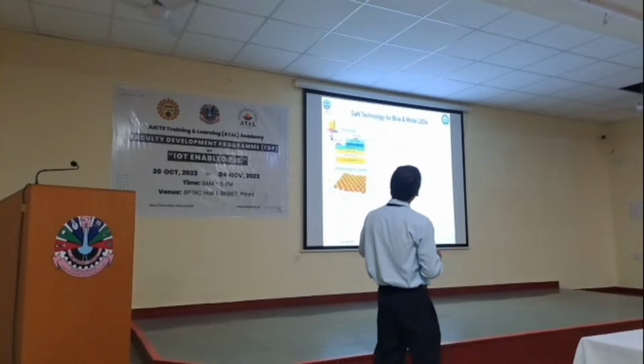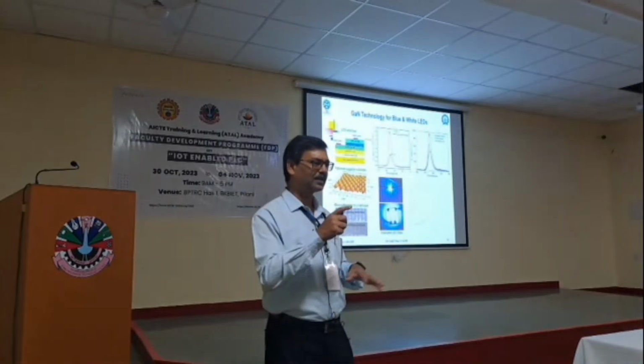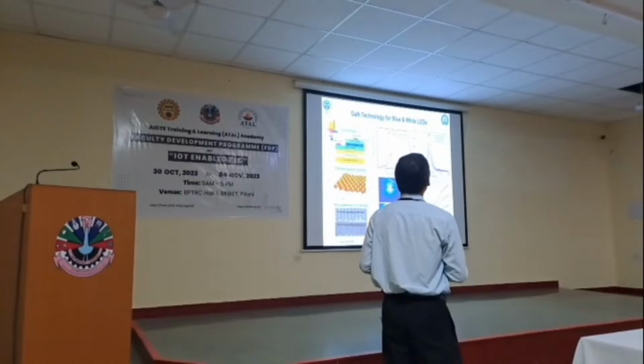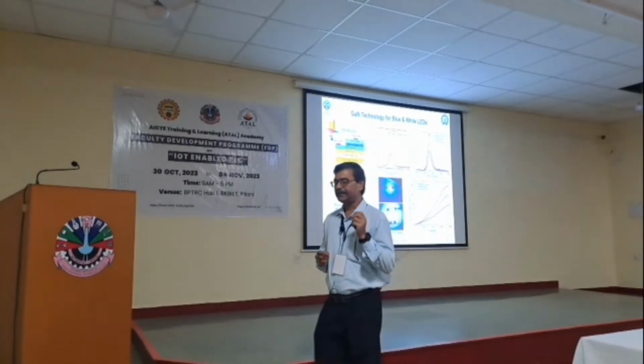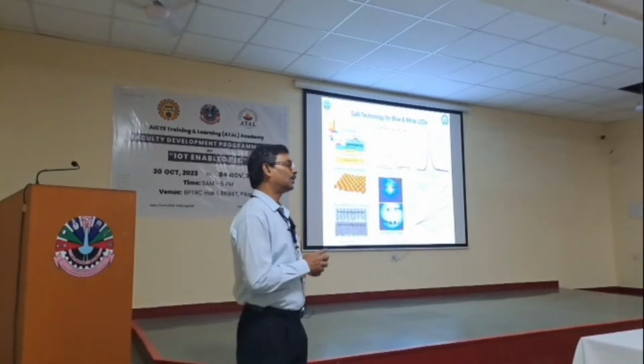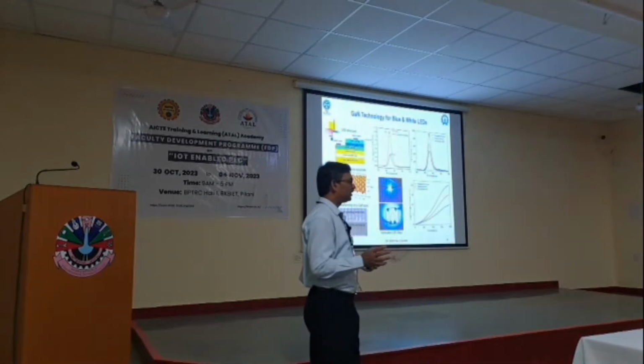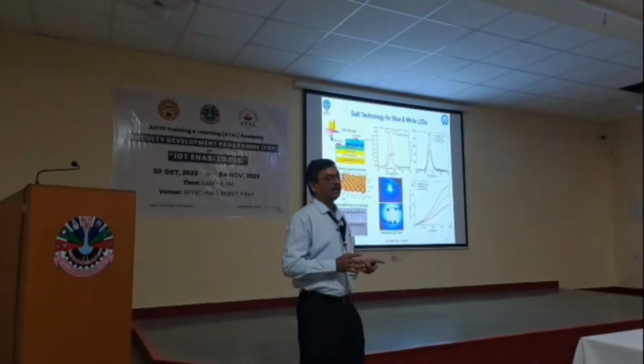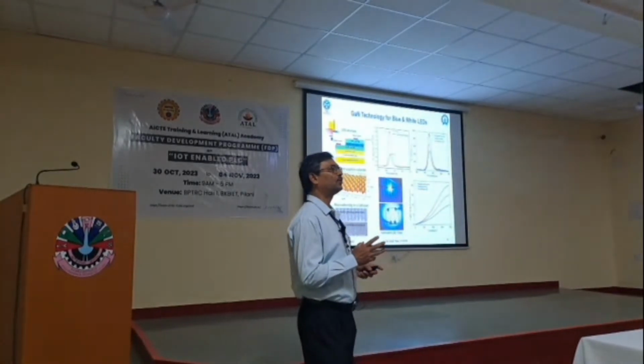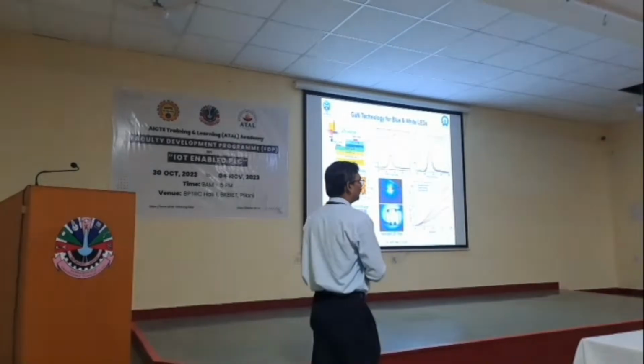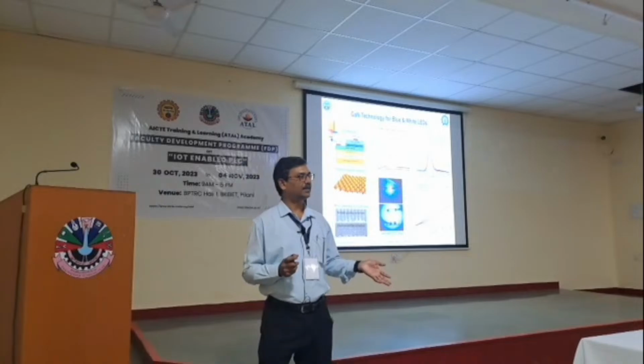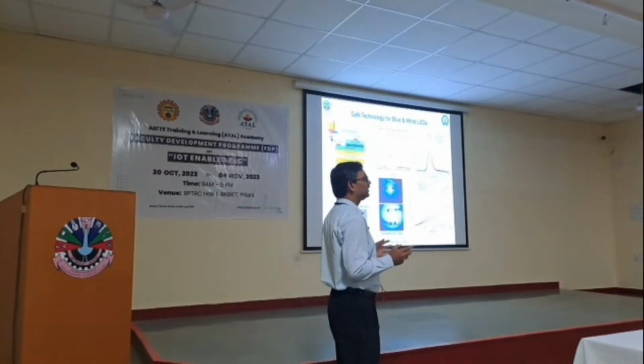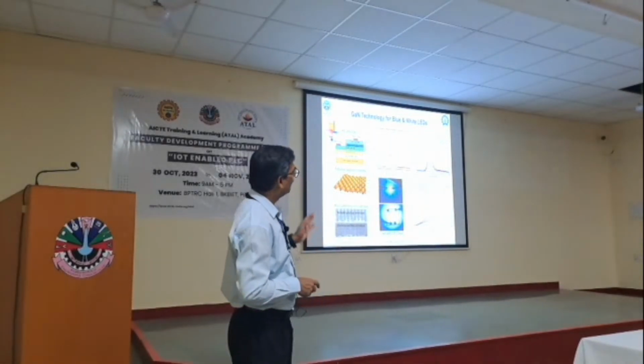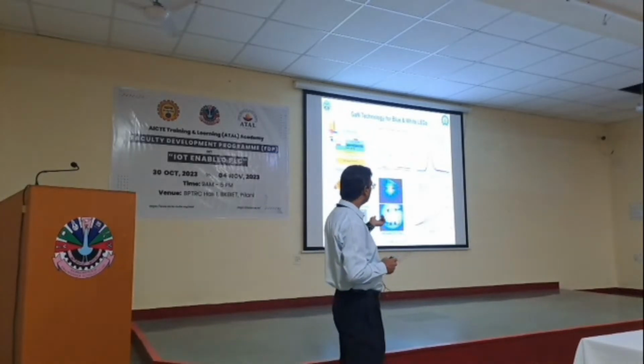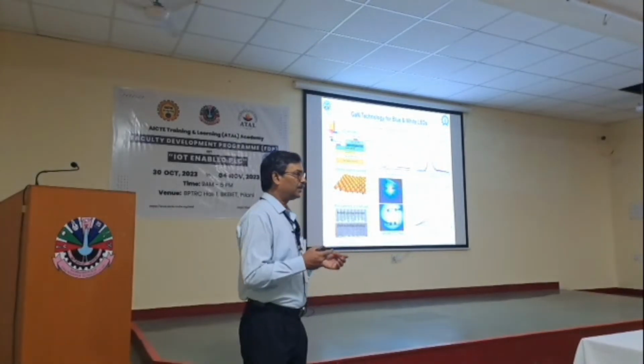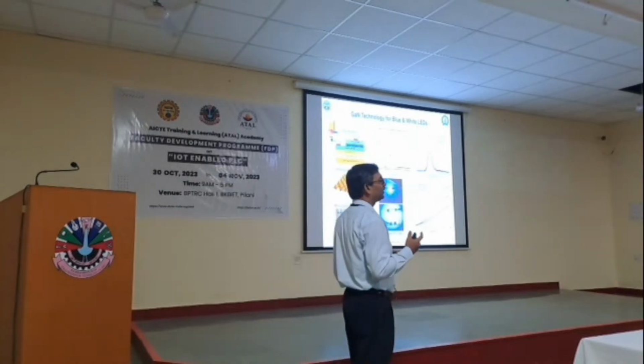What I mentioned, I will go very briefly, quickly, because this is the very inner side of the devices. What I mentioned is LED devices based on gallium nitride materials. And the material is very promising, because so many promising devices we can fabricate using this material. So we have our MOCVD reactor by which we can grow the material. So we can design the devices, we can grow the material, we can fabricate the devices, and after that, we can test and characterize the devices to some extent. Because testing and characterization depends on what type of devices we are fabricating. So we need to augment the equipment for testing of those devices time and again.